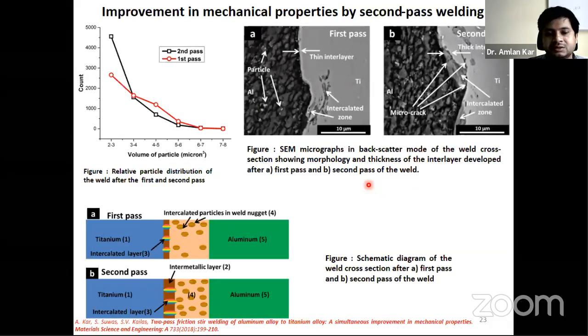So in what we discussed now, we have seen that this continuous deformation mode actually leads to the fine particles, and we have also seen that fine particles actually lead to the higher mechanical property of the weld. Therefore, if we do continuous welding or multipass processing, we can say in your terminology, then we can generate more fine particles. So that we have seen here.